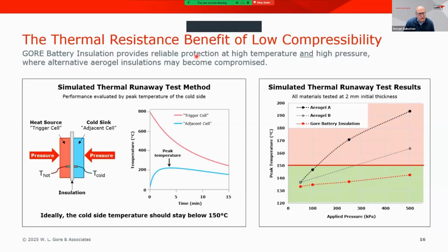No, not the specific initial volume of the battery. I mean, what changes the size of the battery, of course, is any swelling that might occur. But typically in battery module installations, there is some tolerance put into the design for the space between the batteries. And so ideally, you'll try to minimize that as much as possible because that will increase the energy density. And so it's ideal to have the thinnest layer possible as your thermal barrier material, but the thermal barrier material should not affect the absolute dimension of the battery cell.